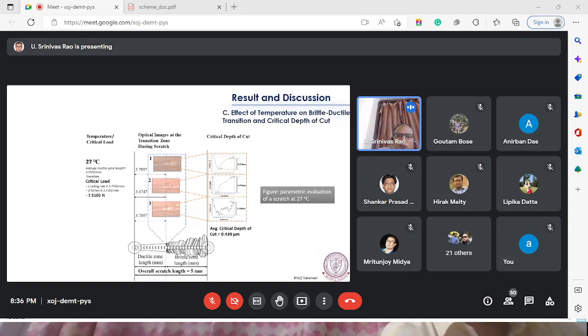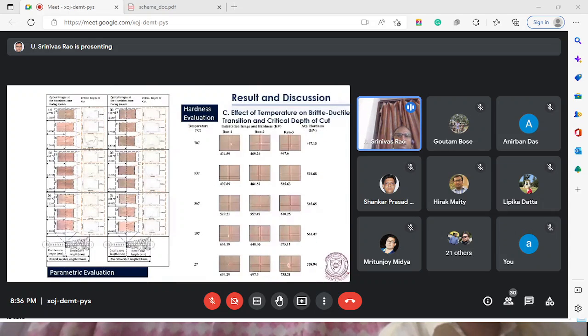The width is evaluated along this section, and from there the depth is obtained. So at different cracks, the same thing is repeated for different conditions, and for every condition the critical depth is found, and that gives an idea of the critical depth with reference to the temperature. And with temperature we know that the hardness and elasticity of the material change. So there was an effort to highlight that and again to model or modify the Bifano model through some empirical constants.